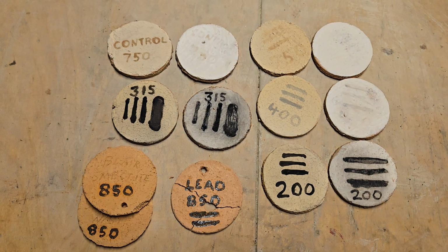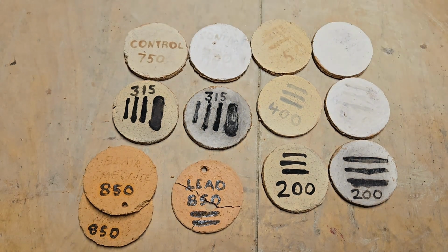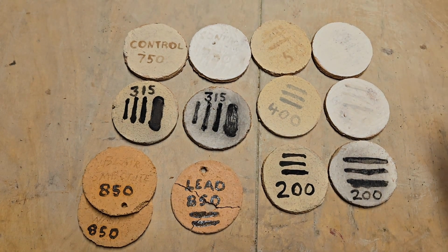Again, these tiles were pre-fired. You could paint a pot after it was fired and heat it up a little bit and get good solid blacks. We know here that with the organic paint, it burns off over time. It's basically carbon. These control ones were discs that were not pre-fired and then added organic paint to them. Totally, almost completely burned off on just a plain paint. This is smectite paint. I'm a little surprised it turned out brown instead of black. I'm not sure why that is.